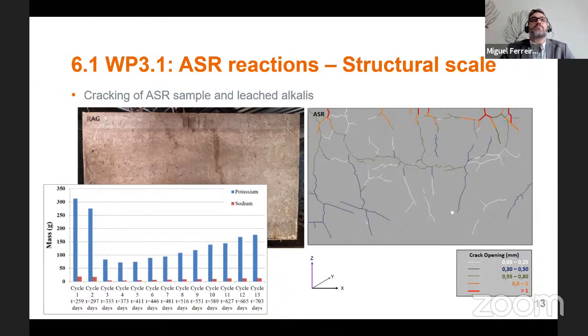And the block itself was cast on top of a metal plate, and this metal plate is having a confinement effect, so it's hindering the swelling in certain XY directions at the lower part of the block. And in that small new figure that appeared there, here we have the measurements of the alkalis as a function of the different water cycles.